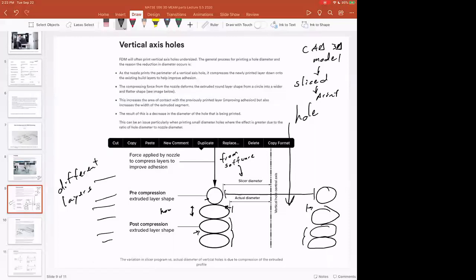how much compression do you get versus how asymmetric the road is versus how wide is the hole to begin with. So if you want to make a 2-inch hole and you get, say, 20 microns of compression, that's not a big deal because the hole size is very big compared to the deformation. But if you want to make a 1 millimeter hole, or if you want to make a 5 millimeter hole, and you're getting 0.5 millimeter of compression, that can cause a big difference.